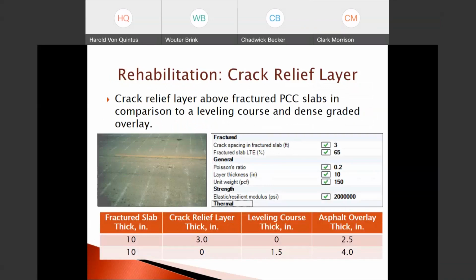Again, looking at a crack relief layer above a fractured Portland cement concrete. So we're using the same reflective crack mitigation strategy, but this is for a crack and seat or fractured PCC slabs, in comparison to using a leveling course and dense graded overlay itself. So I've shown the inputs here. We have a fractured crack spacing of 3 feet. That's the crack spacing in the PCC for the fractured slabs. And then we have the load transfer efficiency, in this case, of 65%. An elastic modulus of the PCC above the cracks of basically 2 million PSI.